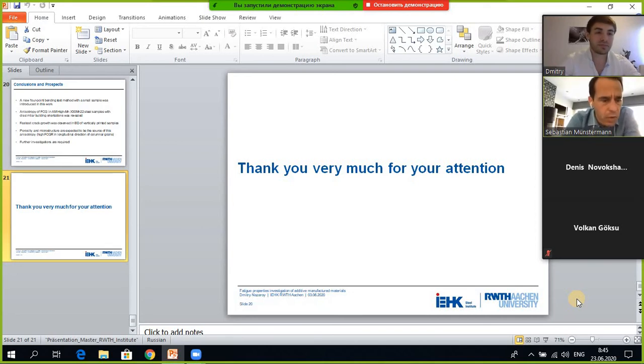Okay. One last question from my side, which is a very short one. You pointed out some anisotropy of the fatigue properties, and, to my understanding, very correctly argue that this is the result of building the sample. Did you also check the anisotropy in the quasi-static strength properties by tensile tests? Okay, no, actually I did not investigate that. In our institute they already investigated exactly this steel for tensile test anisotropy, for specimens built in different building orientations. So it was not meaningful to do the same test. I did something which was not investigated before. Okay, so I'm done with my questions. I don't know about the others.